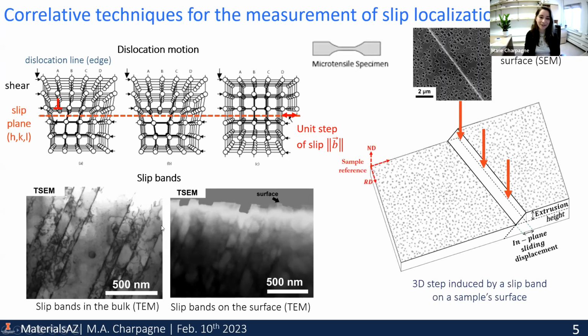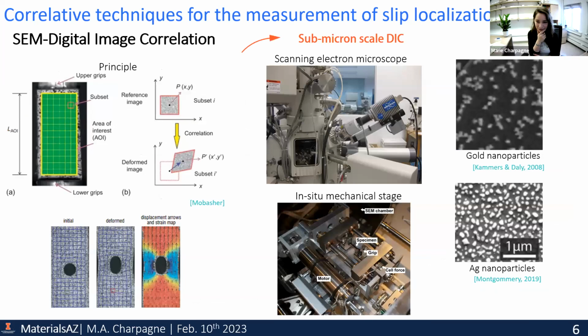So summarizing, this is by looking in transmission. When we take a microtensile specimen and pull on it, we can see, looking from the top of the specimen, those very small extrusions in secondary electrons in the SEM. And these are the signature of a 3D slip band. The slip band is a 3D object, right? So the challenge is, of course, measuring this step. And recently, my colleague JC has developed very high resolution digital image correlation to track how these slip bands emanate on the surface and what signature in displacements they bring onto the surface of these microtensile specimens.